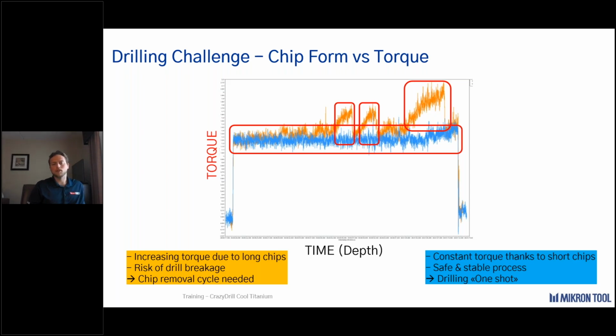And after that certain depth is achieved, now we see drastic increases in torque. When we see drastic increases in torque, this will generally be a symptom, or a symptom before a drill failure, to put it mildly. As we see these giant jumps, we're applying much more mechanical force onto the drill body itself, and we increase the likelihood of a catastrophic drill failure. This is something we absolutely must avoid if we're machining high value parts.